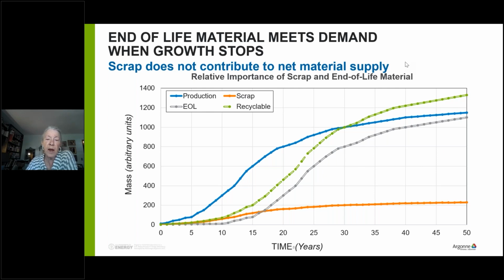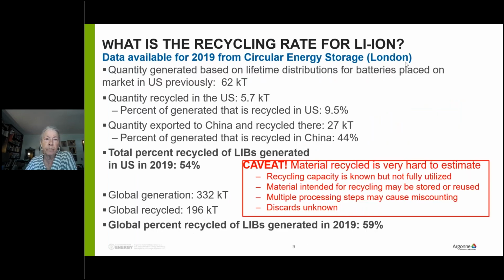And the scrap greatly exceeds the recyclable material from end of use until something like 15 years out from the beginning of production, which means that recycling plants are relying on scrap for their feedstock now. And that's a key point that is often overlooked. And it in fact is the enabler for a profitable recycling industry in the early years of battery production. So what we've just shown is that recycled material is not going to be a huge contributor, at least out till 2030.